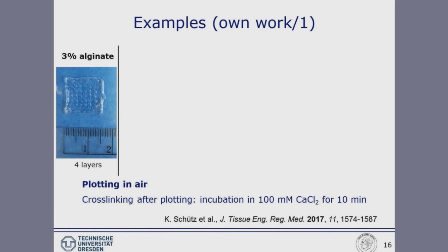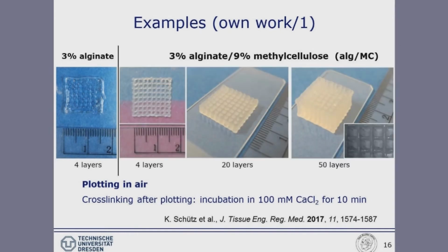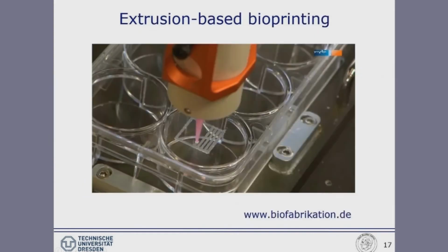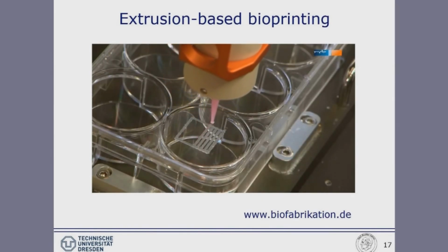So what we did was extremely simple. We just blended the alginate with another biopolymer, methylcellulose, 9 weight percent. With this, we achieved a much better hydrogel with a much more suitable viscosity. Here we nicely could print even 50-layer scaffolds, with very nice and still well-shaped scaffolds. Here photographed from Z direction. And I can show you the printing process with this little video film here.